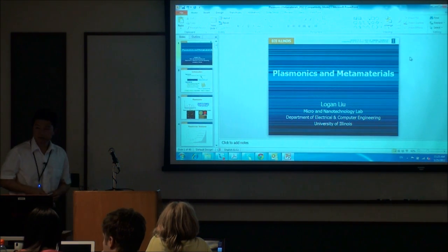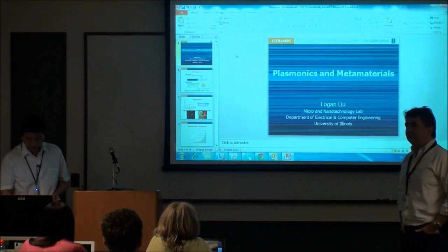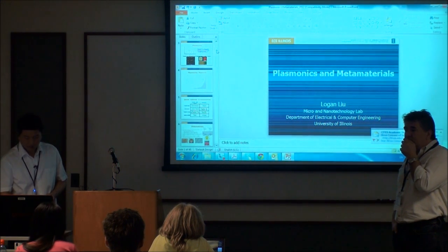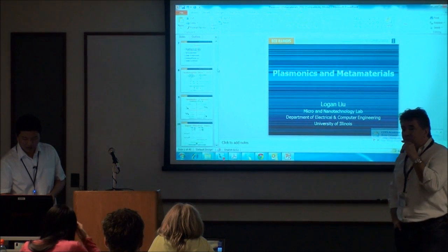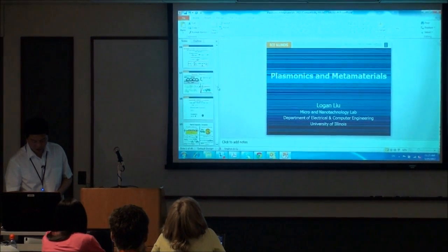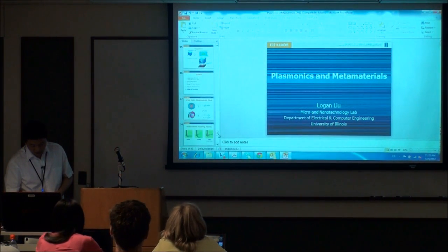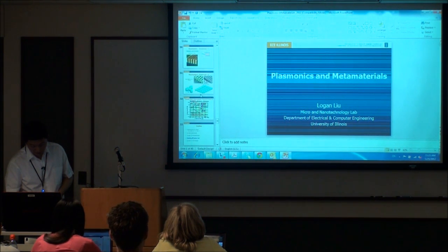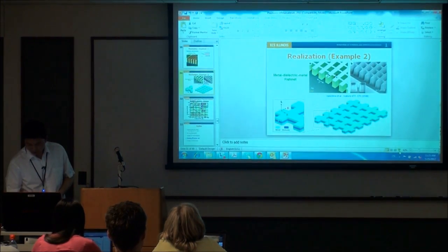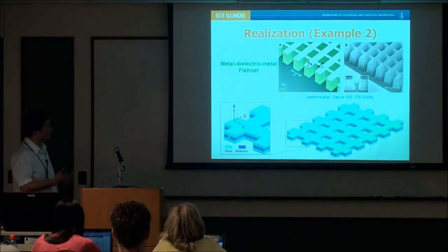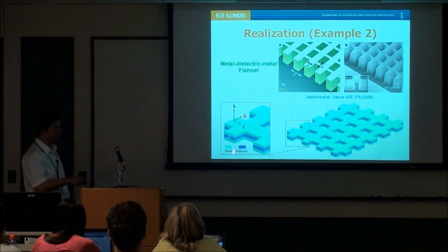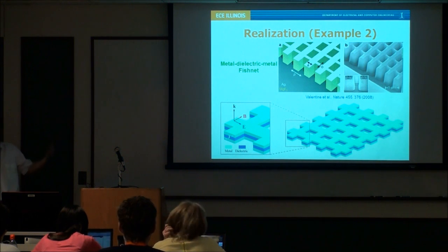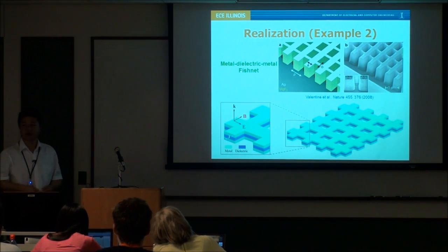So in the experimental setups that you described for these negative epsilon, negative mu materials, are they isotropic with regard to directionality? Well, they're not isotropic. It really depends on the way that you create it. For example, let's use the simple so-called multi-layer stacking structures, and your wave vector has to be perpendicular to these layers. If you have other waves propagating in other K vectors, then you will not have this property at all.